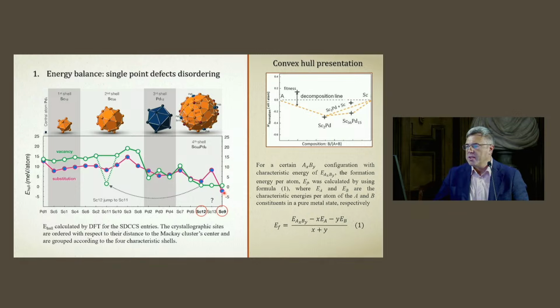For example, scandium-9 site gives even negative values with respect to the convex hull, and similar behavior is also seen for scandium-12 position, but differently for our experiments, no hints from this plot for scandium-13 position.